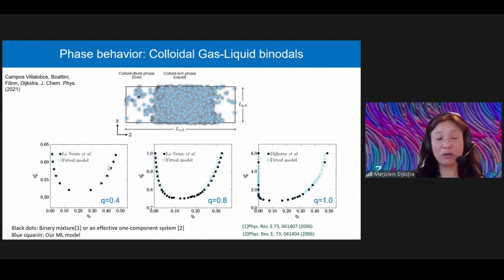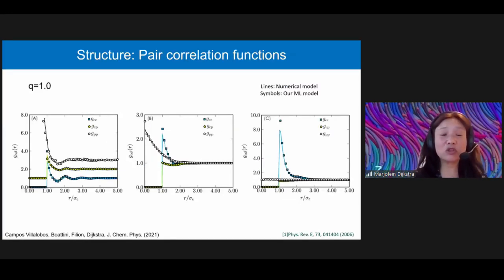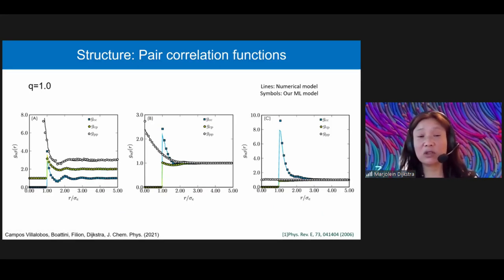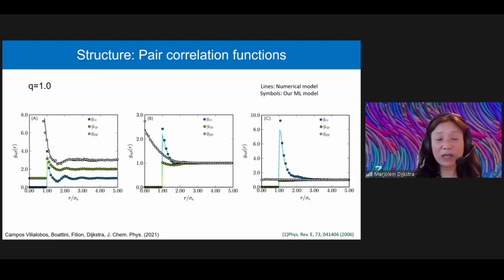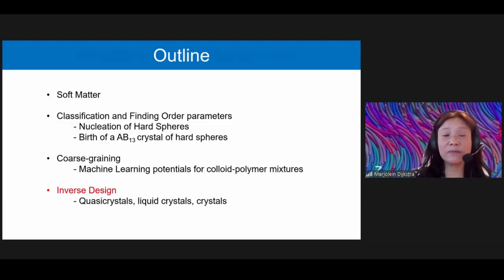The blue symbols are the ones with the machine learning fit, and the black symbols are earlier data using either the true binary mixture or an effective one-component system where we use this numerical evaluation of the higher-body potential. And also here we find excellent agreement between the machine learning fit and the previous data. We can also look at structure, pair correlation function, and also there we find very, very good agreement between the two sets of data. So we are now extending this towards charged colloids, anisotropic colloids, but also ligand-stabilized nanoparticles where we can integrate out the degrees of freedom of the ligands on the nanoparticles.